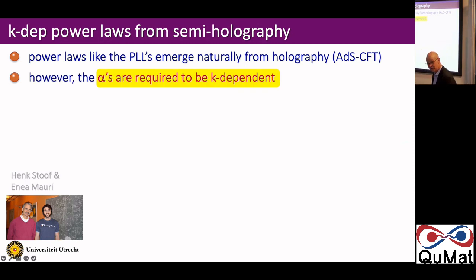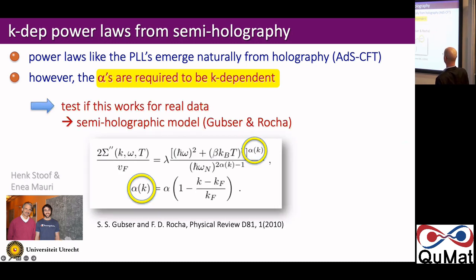But there's an absolute condition. This is not some nice to have thing that Henk just likes because it fits his worldview. He can't not do this in the theory, that the alphas, these power law exponents, have to be dependent on k. So when k is equal to kF, there's no k dependence there. And as k minus kF starts to grow, these alphas have this k dependence, and that means the line shapes have to be asymmetrical.